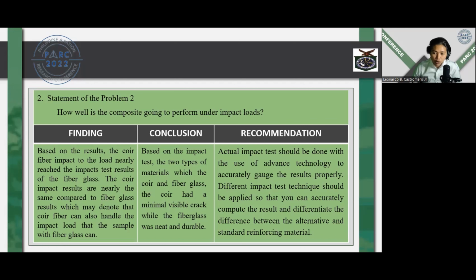Conclusion. Based on the impact test, of the two types of material, the coir and fiberglass, the coir had a minimal visible crack while the fiberglass was neat and durable. Since the fiberglass is the basis of this study, the researchers conducted the test to ensure the amount needed for the coir to be able to replace synthetic fiberglass composite material.